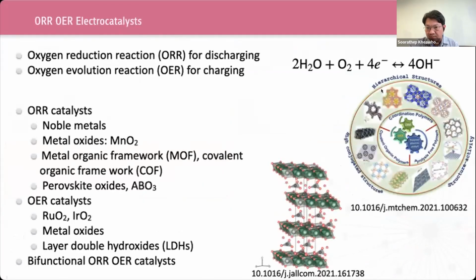Typically, an ORR electrocatalyst is not stable in oxidizing condition. Also, an OER catalyst is not stable in reducing condition. Noble metals are excellent ORR catalysts, but they are too expensive. Metal oxides, such as manganese oxide in certain phases and forms, exhibit excellent ORR performance in strong alkaline electrolytes. We are also working on metal organic framework and covalent organic framework. You can refer to our recent articles here with this DOI.